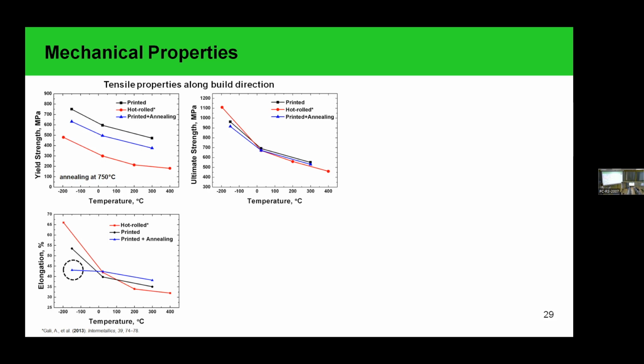We don't lose in ultimate strength after annealing, but we see that the yield strength of the printed material is much higher, and we lose only 100 megapascals after annealing, but it is still higher in comparison with the hot rolled material. Also, for the as-built materials, we observe the same tendency as for the hot rolled one, where we see an increase in ductility at cryogenic temperatures. We expected the same for the annealed materials. We see that it increased a little bit at room temperature and at 300 degrees Celsius, but we didn't observe the increase in ductility at cryogenic temperature.